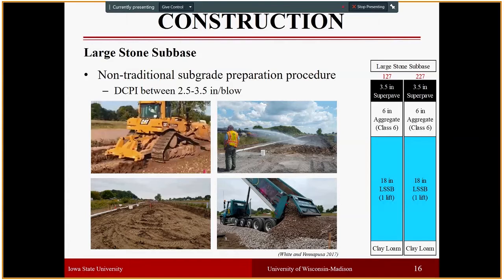And for large stone subbase, again, we have 7 different large stone subbase test sections. Cells 127 and 227 have 18-inch thick large stone subbases. The idea was that the geotech group wanted to build one of the large stone subbases in 2 lifts instead of 1 lift, but due to construction difficulties, it didn't really work out well in terms of compaction and that sort of thing.